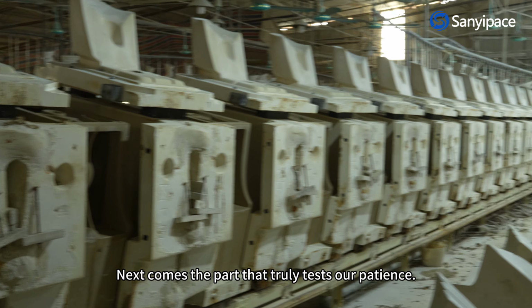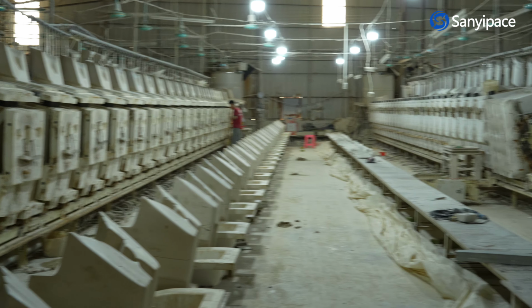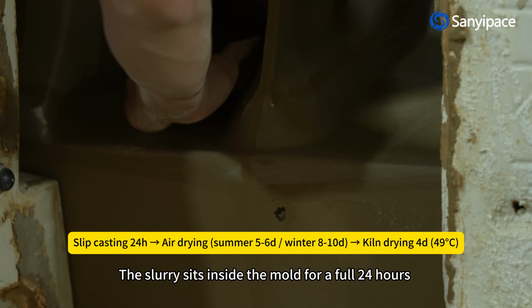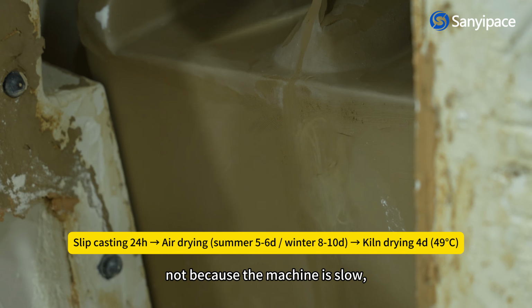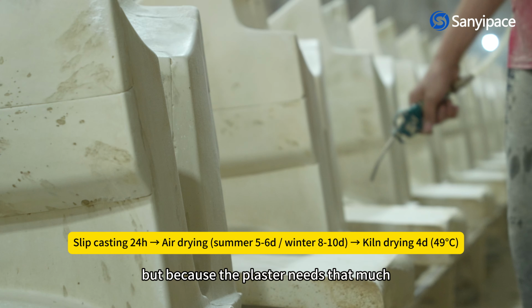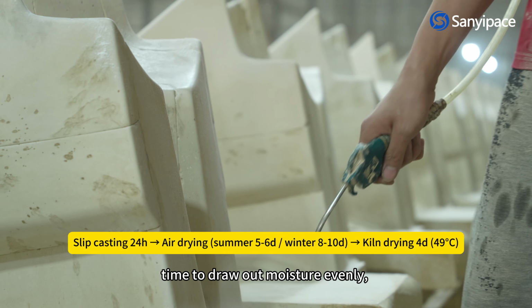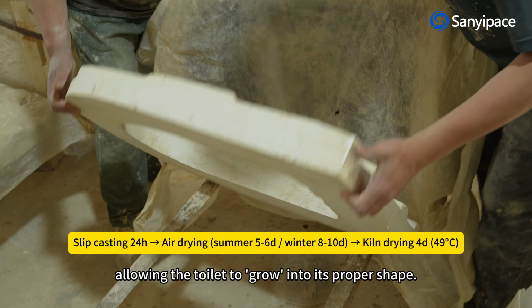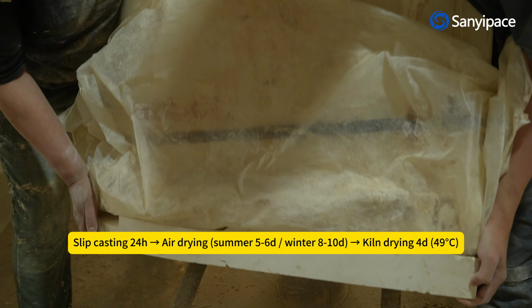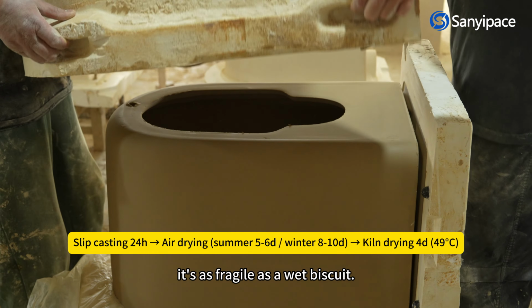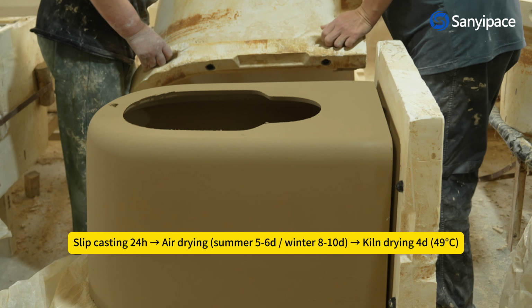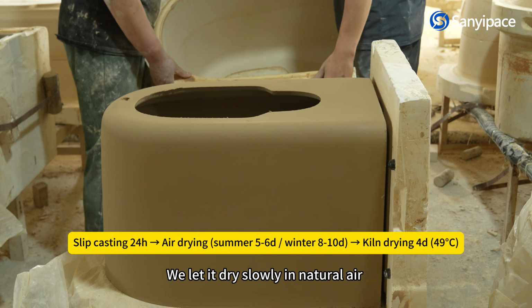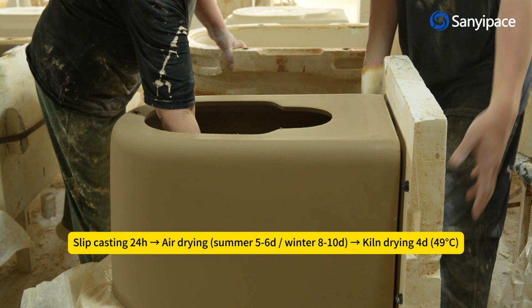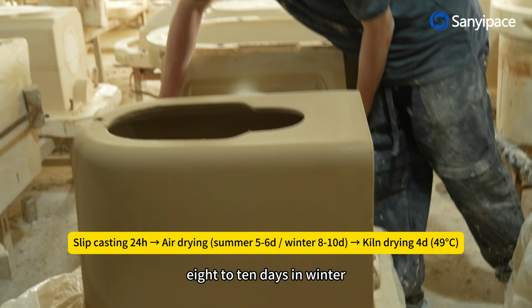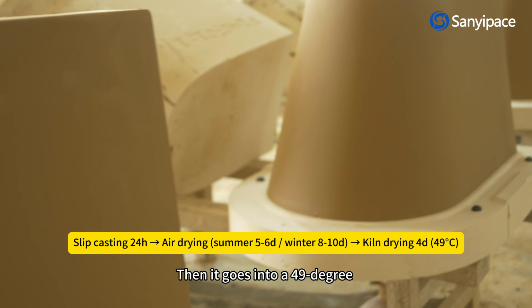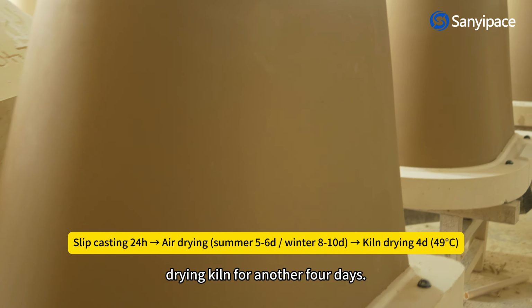Next comes the part that truly tests our patience. The slurry sits inside the mold for a full 24 hours, not because the machine is slow, but because the plaster needs that much time to draw out moisture evenly, allowing the toilet to grow into its proper shape. Once the mold is opened, it's as fragile as a wet biscuit. We let it dry slowly in natural air, 5 to 6 days in summer, 8 to 10 days in winter. Then it goes into a 49-degree drying kiln for another 4 days.